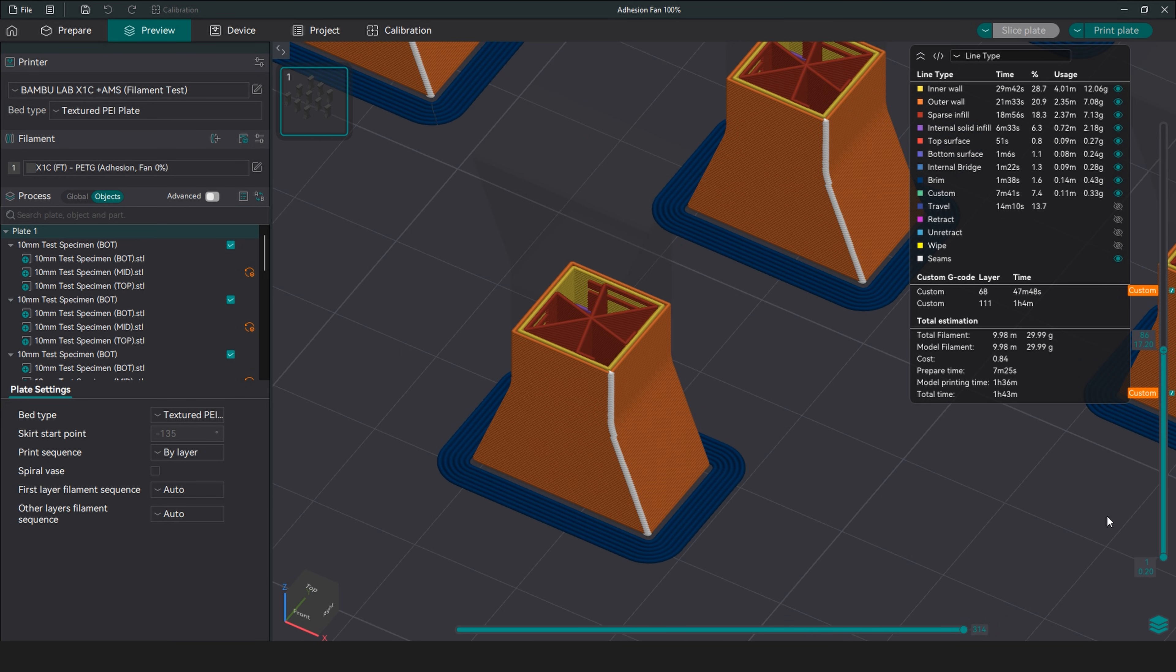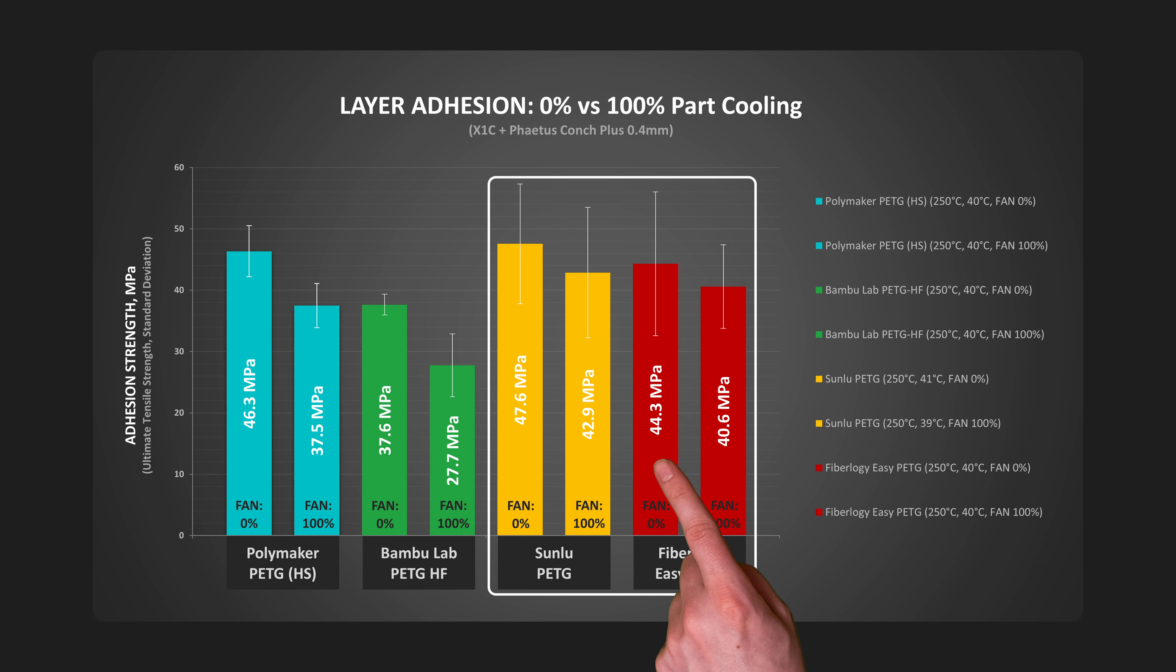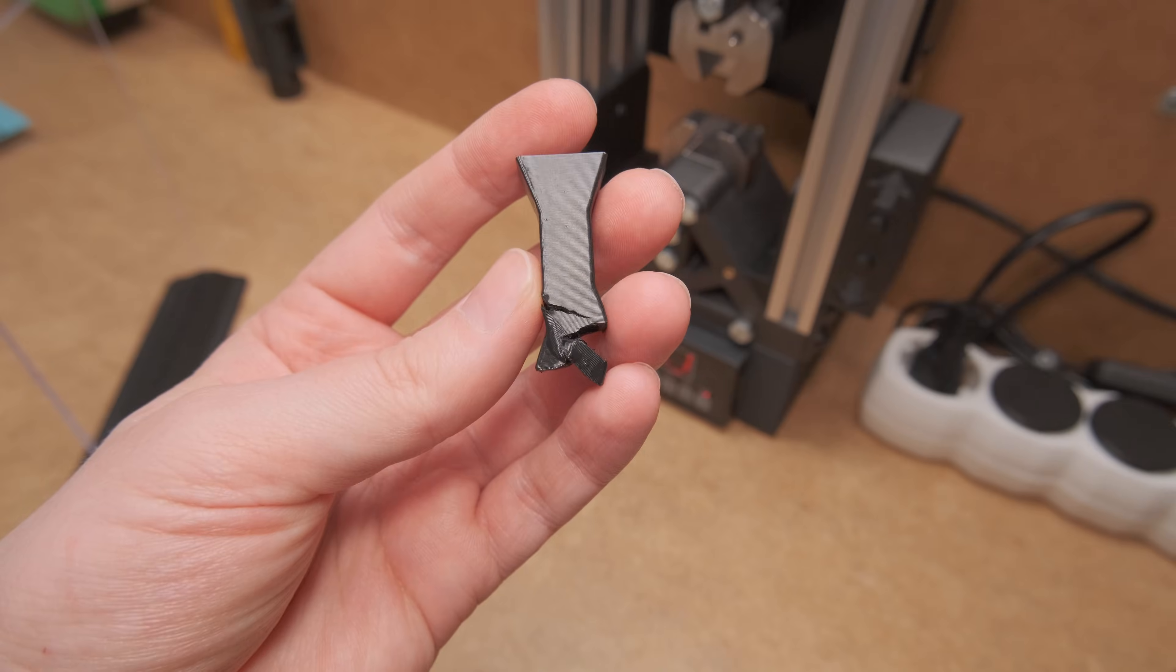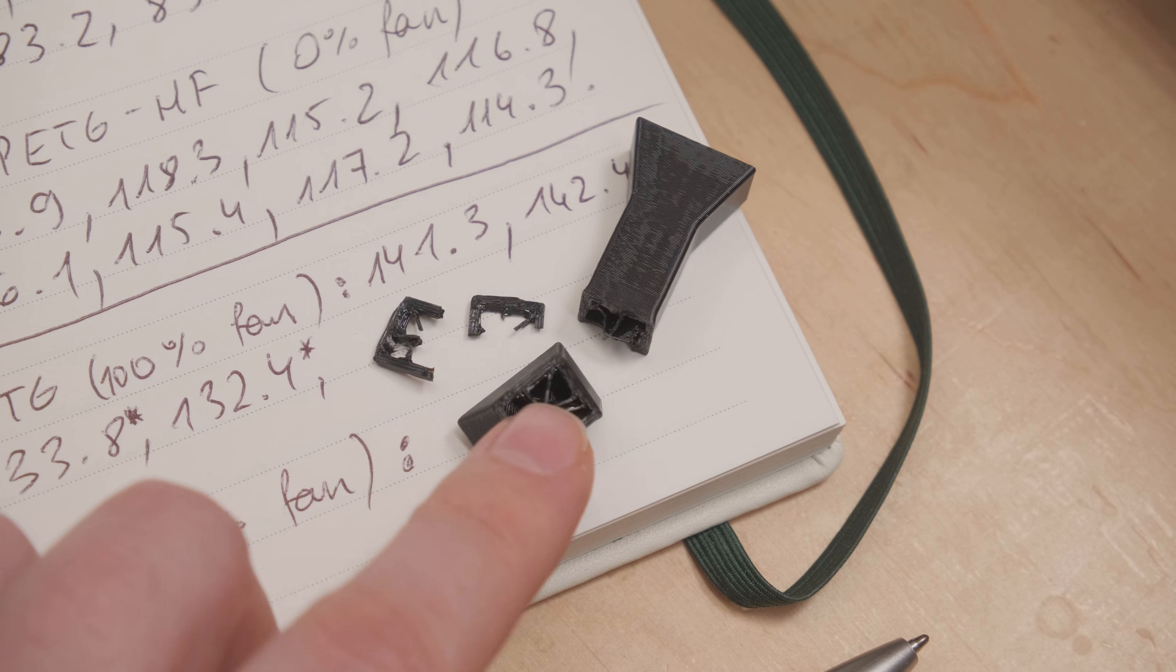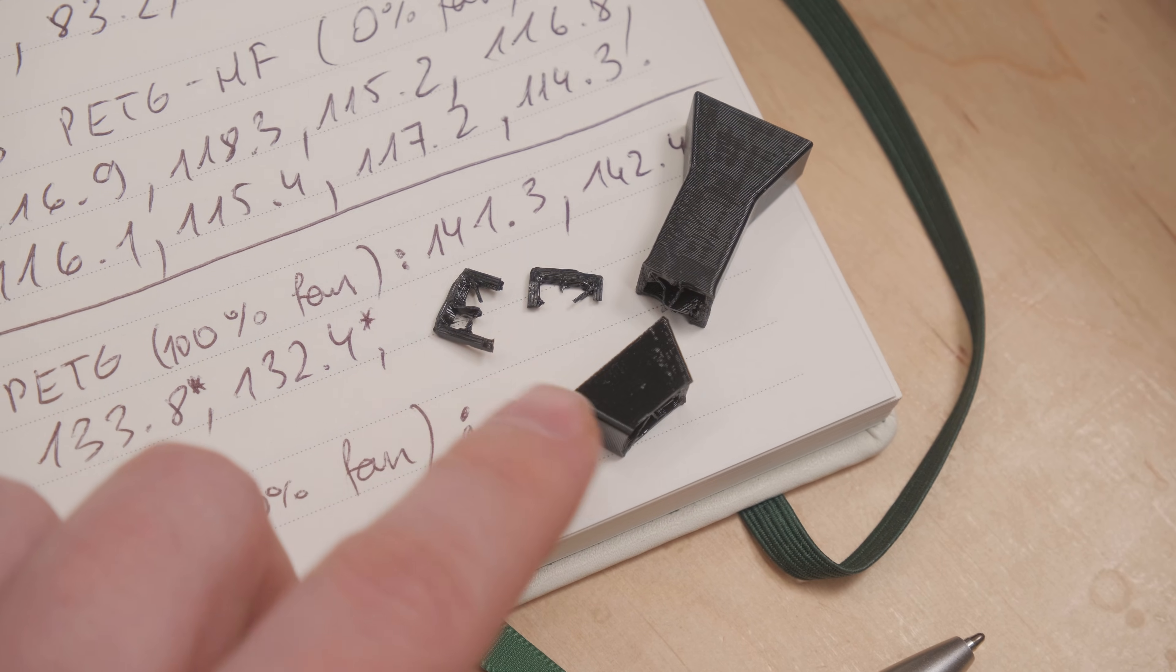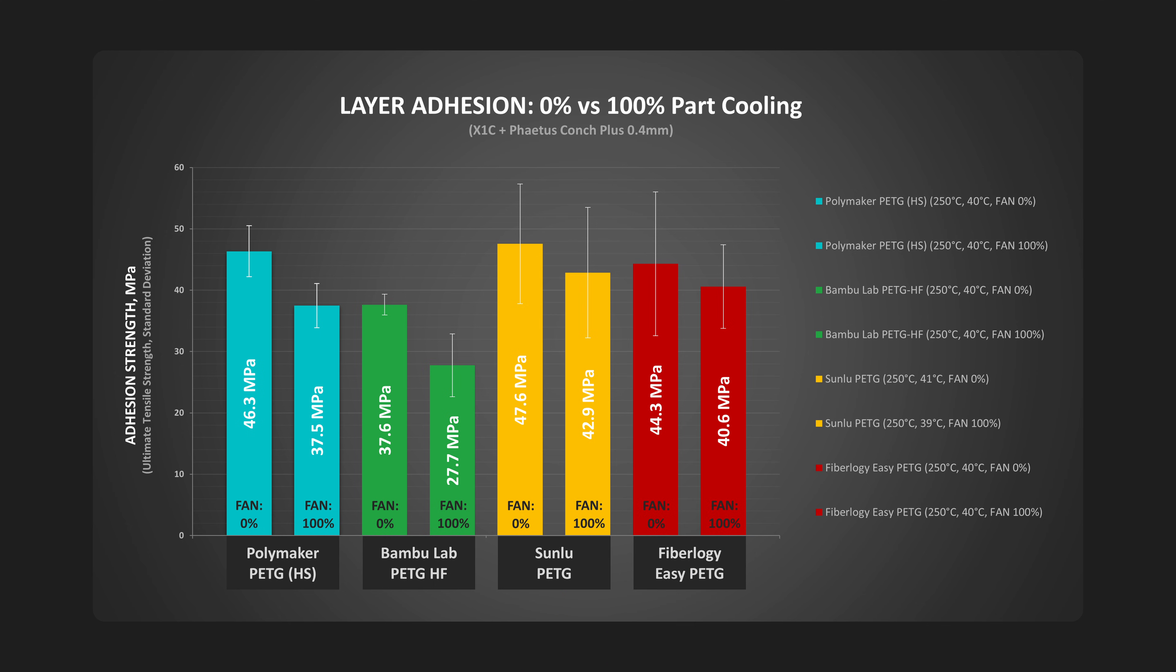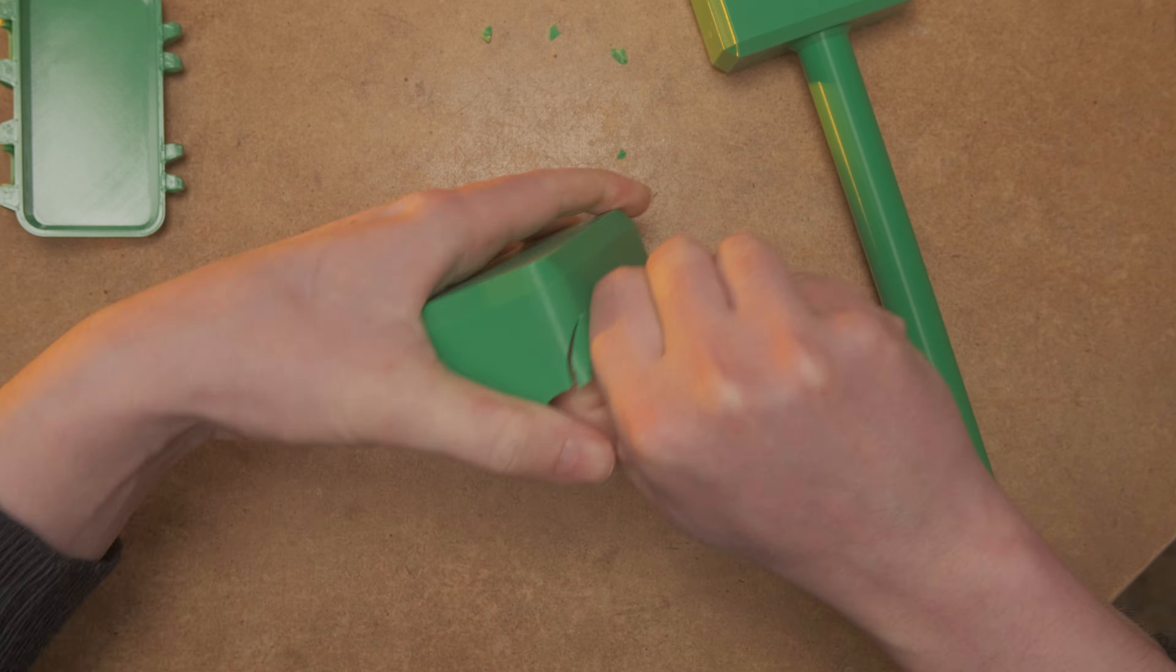However, during this testing, both regular PETG variants from Fiberlogy and Sunlu showed quite a concerning trend. Some samples just deformed and some exploded into multiple pieces in the thick top sections. Meanwhile, Polymaker's high-speed PETG had a very similar layer adhesion level and didn't suffer from any of those problems. This means this filament will produce strong prints that you can rely on, which is the first huge advantage of it.